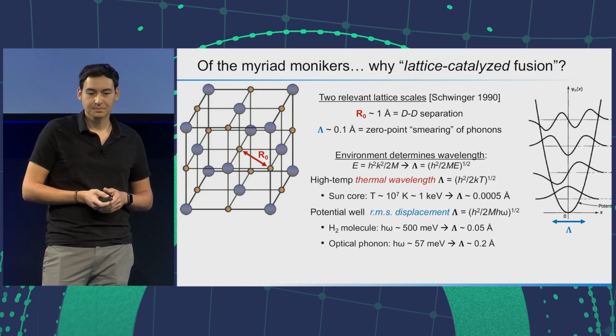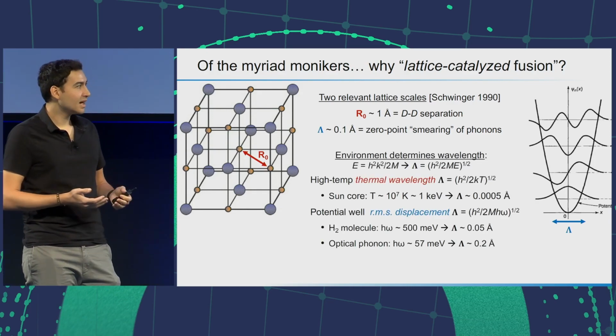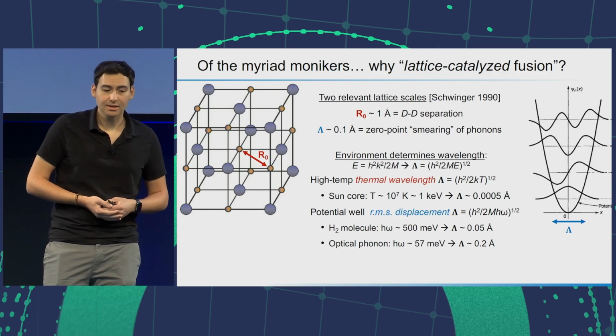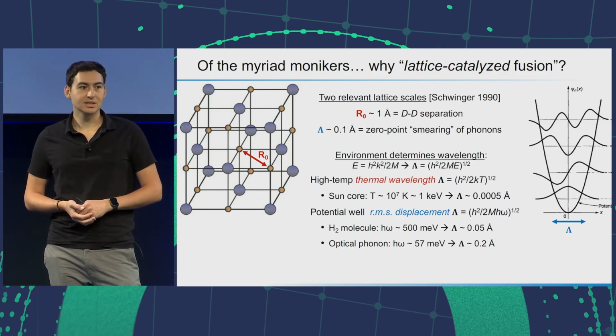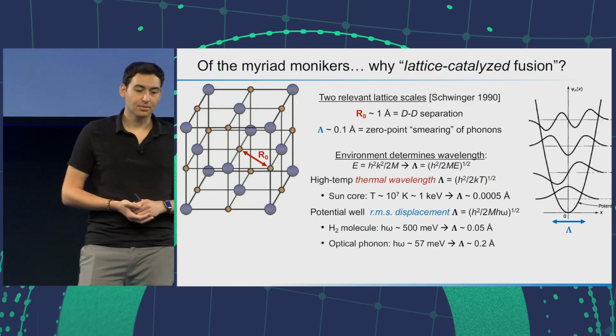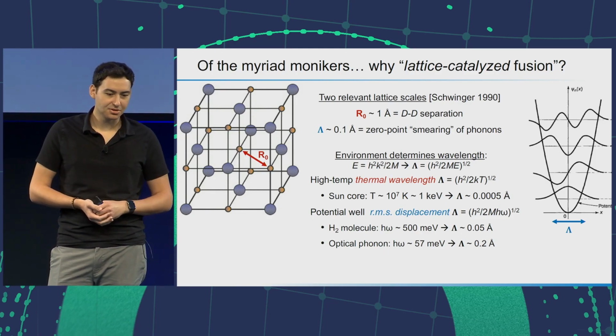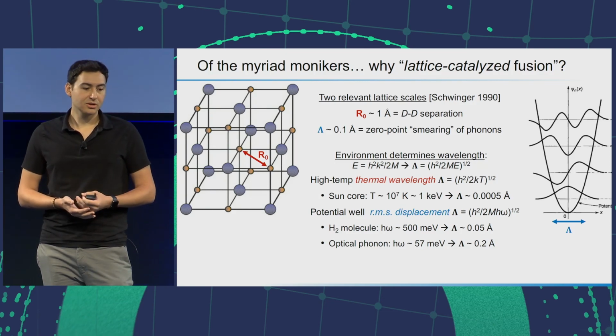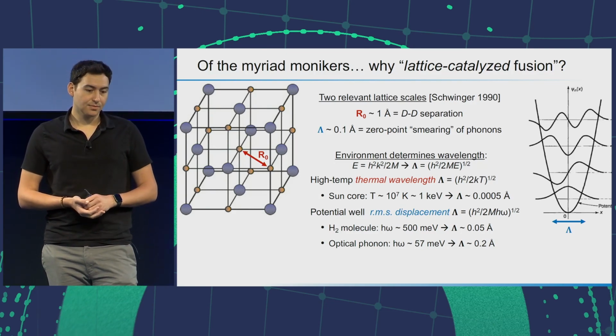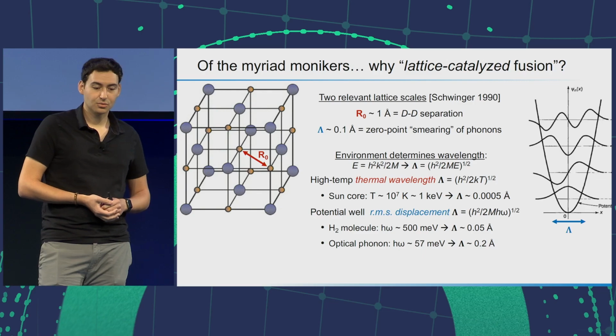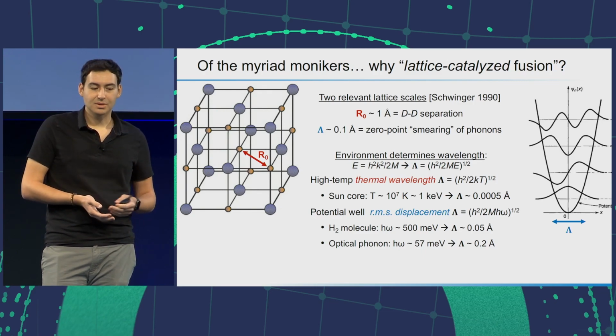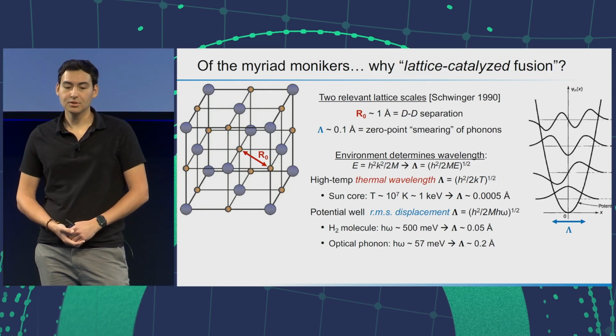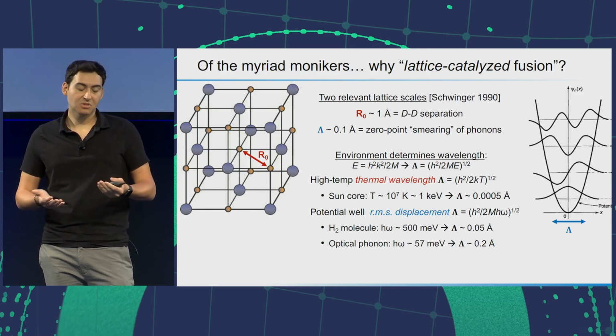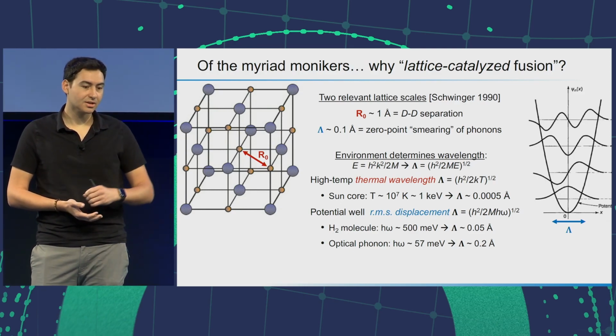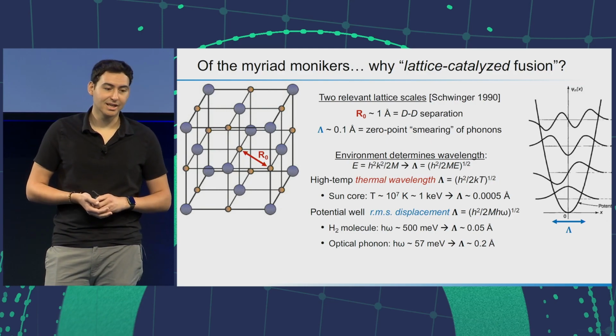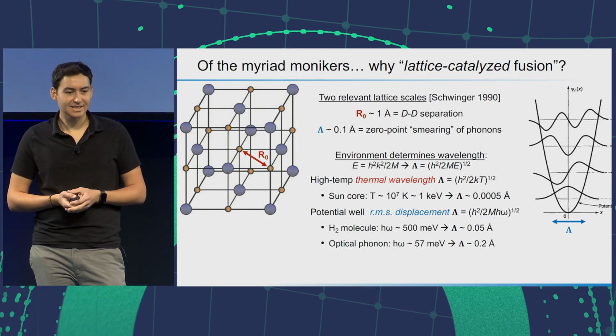his calculation. Just to give you a sense of scale, the environment is what's determining the wavelength. And so if you imagine 15 million degrees in the sun, and we compute this thermal wavelength, we see it's quite small, 0.0005 angstroms. But when we go to low energy systems, because the lambda depends inversely on the square root of omega, when we look at a hydrogen molecule, or more interesting to us, optical phonons, we see that scale reaches around 0.2 angstroms, which starts to get within a stone's throw of this R0 quantity at 1 angstrom. So that's why the lattice is interesting.